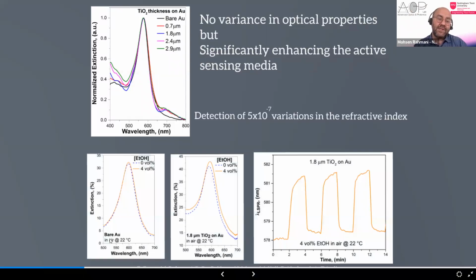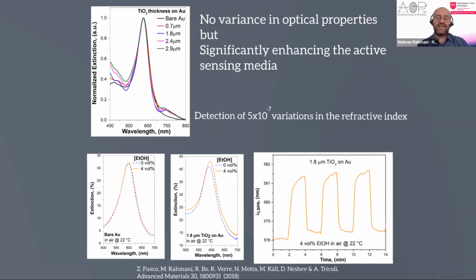Here, as you see in the results, when we have only plasmonic nanostructures in this graph and we purge 4% of ethanol, the change in the plasmonic resonance is not remarkable. But when you have this 1.8 micrometers, which is explained in the paper to be the optimum thickness, the best thickness, we get a very remarkable change in the plasmonic resonance. And as you see, it's very repeatable. When you purge the ethanol, the resonance shifts, and when it's stopped, it goes back to the same resonance. And again, you can repeat it. It's very durable, this kind of sensing.